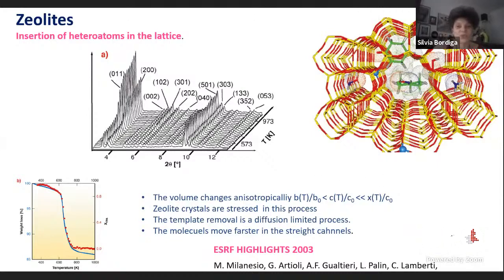In particular, by introducing the titanium, we observe a tension inside the lattice, which is not isotropic, and the effect is different in the different cell parameters. And this is an important information because it testifies that the titanium is inserted inside the lattice, and also is telling us that it's not possible to introduce a huge amount of titanium inside the lattice. Conversely, it has been proved that the active titanium is just a titanium which is isolated inside the lattice of the zeolite.